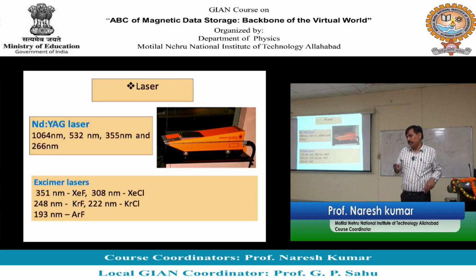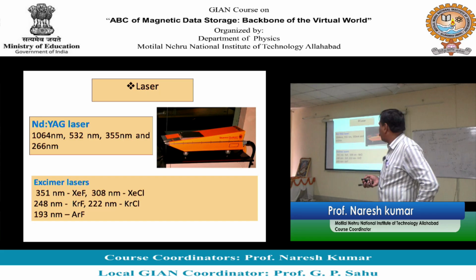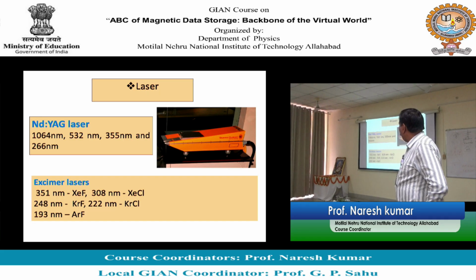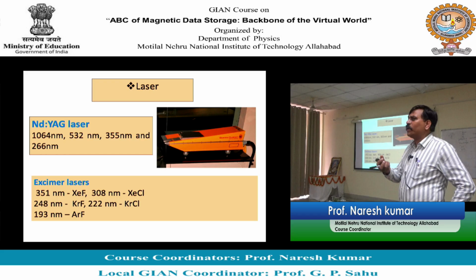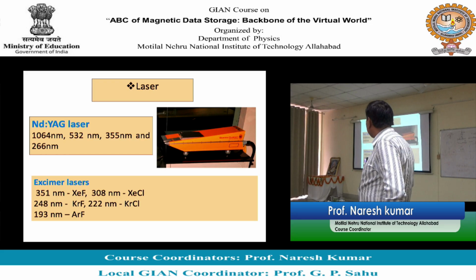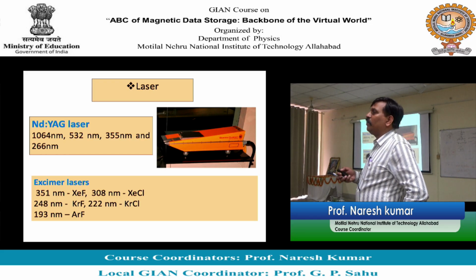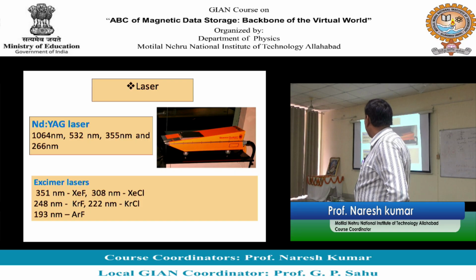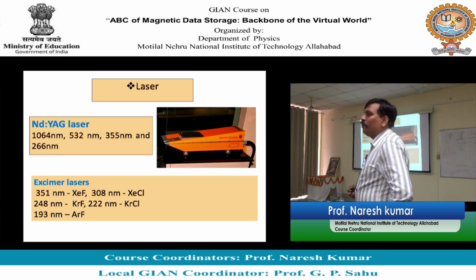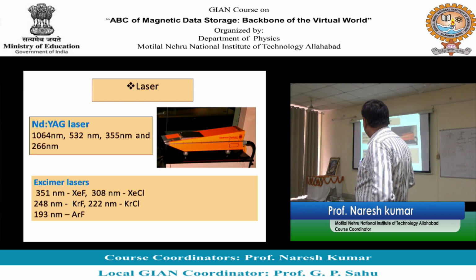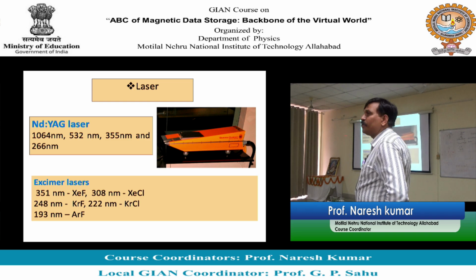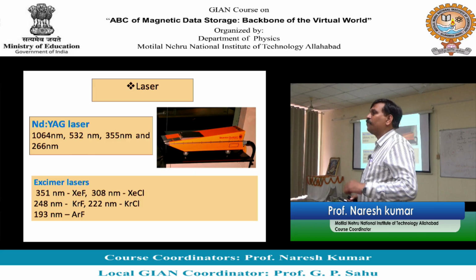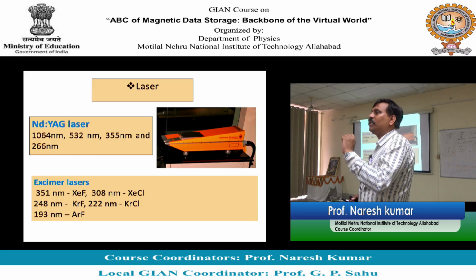And the most important part of this setup is this laser. We are using an Nd:YAG laser. If you look at the physics of the Nd:YAG laser, it is basically yttrium aluminum garnet, Y3Al5O12 is the structure, and it has about 1% doping of neodymium in the YAG crystal. Fundamentally, it gives you 1064 nanometer. 1064 is in the IR range, right? You don't see the laser light.